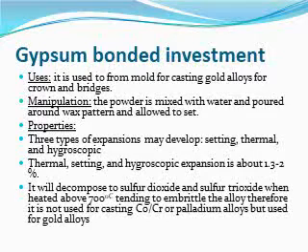الsetting والthermal والhygroscopic expansion تكون about 1.3 to 2%, and it will decompose to sulfur dioxide and sulfur trioxide when heated over 700 degrees, tending to embrittle the alloy. Therefore, it is not used for the casting chrome cobalt or palladium alloy. just نستخدمها للجولد alloy اللي هي تعتبر النقطة المهمة عندنا بالجبسم bonded investment material.